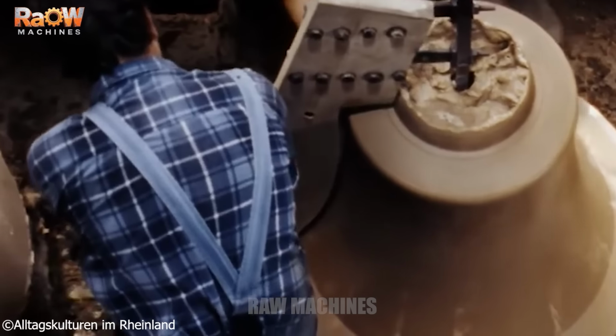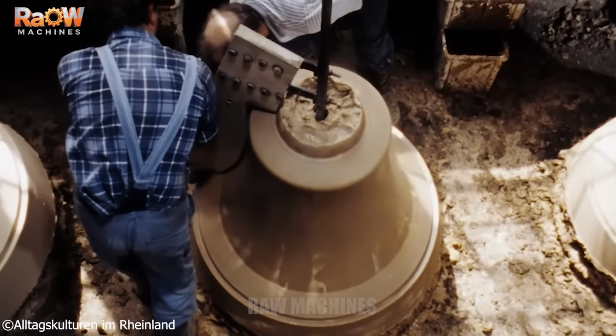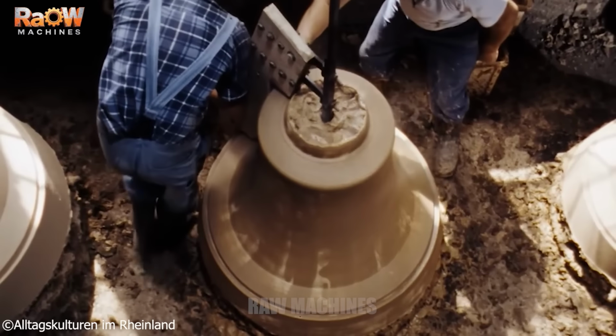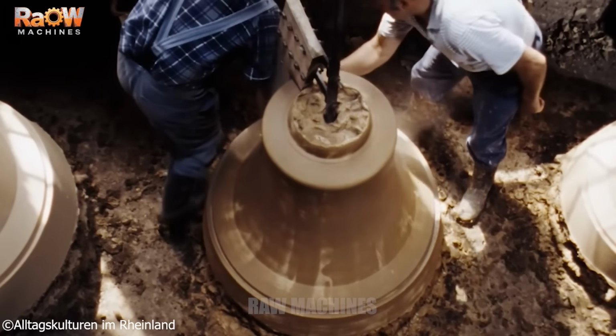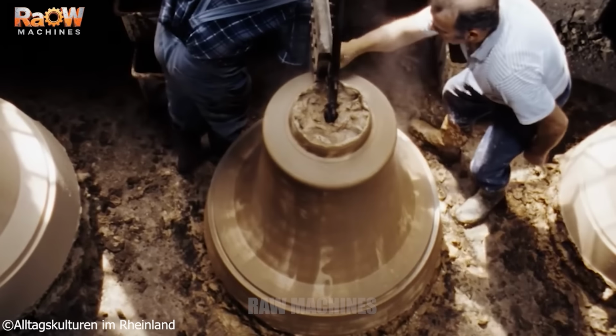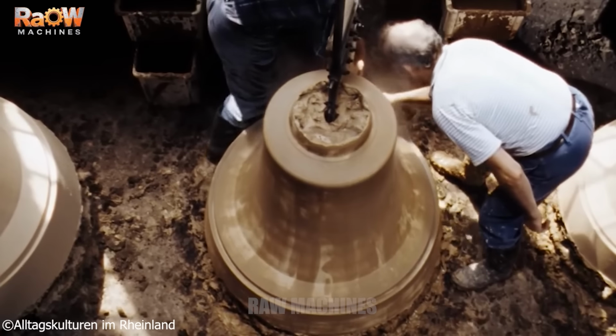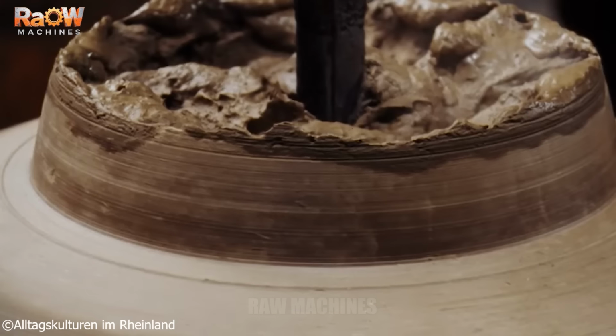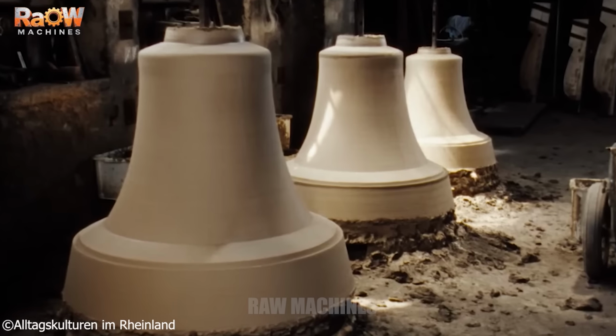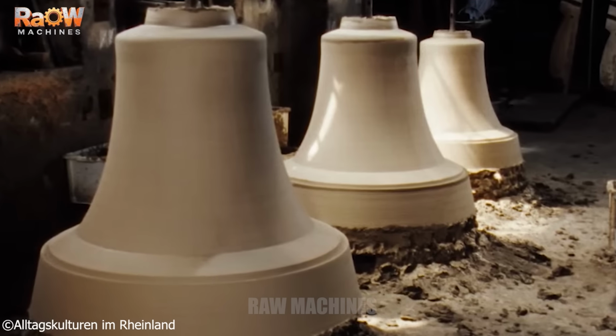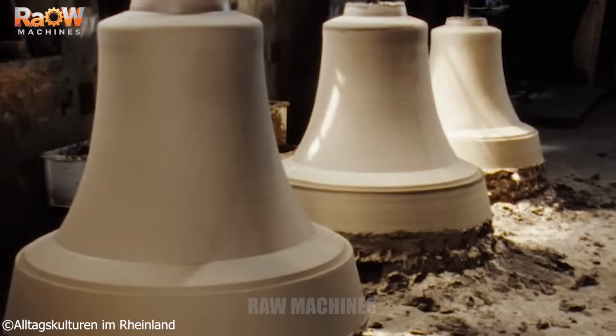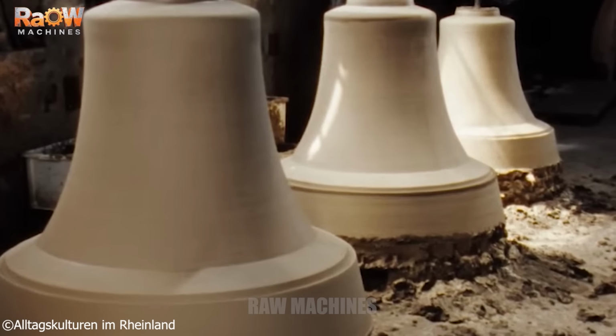The final fine layers are applied when the internal temperature of the core exceeds 100 degrees Celsius. At the top of the core, a technical groove is formed to accommodate the suspension loop of the bell clapper. The total time required to produce the cores for the 3 smaller Merzig bells is 11 days. Once fully dried, the core surface is coated with graphite, serving as a release agent.